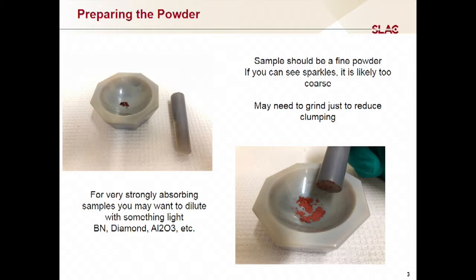Depending on your sample, this can be either something that you can just grind and grind and grind, or it may be something that you want to be very careful about because you can actually induce changes in your sample this way. It's very difficult to grind something so fine that you start to see peak broadening, so that's generally not a concern. What is a concern is that the act of grinding, at that point you get some very high pressures and you get some elevated temperatures, and so you can actually induce phase transformation. And actually, in grad school, this was an interesting way that people prepared their samples. They were making what are called co-crystals. So this is something that's fairly big in the pharmaceutical industry.